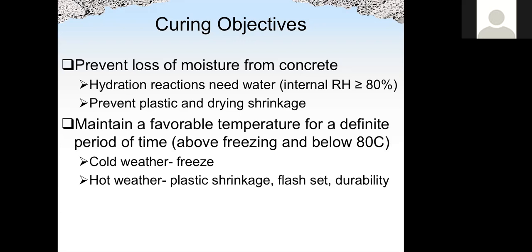And the second goal for curing is to maintain a favorable temperature for a certain time. The temperature cannot be too low, otherwise the concrete will freeze. We call that freeze-thaw damage. And the temperature also cannot be too high. Then we could have problems such as flash set, plastic shrinkage, or other durability issues such as delayed ettringite formation. So the temperature should be moderate.